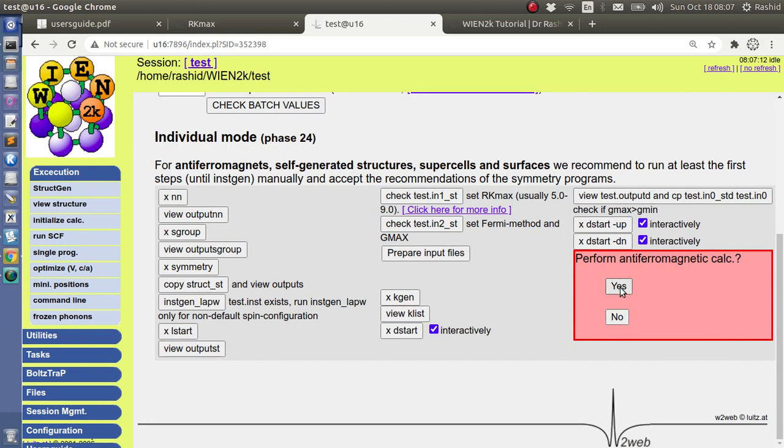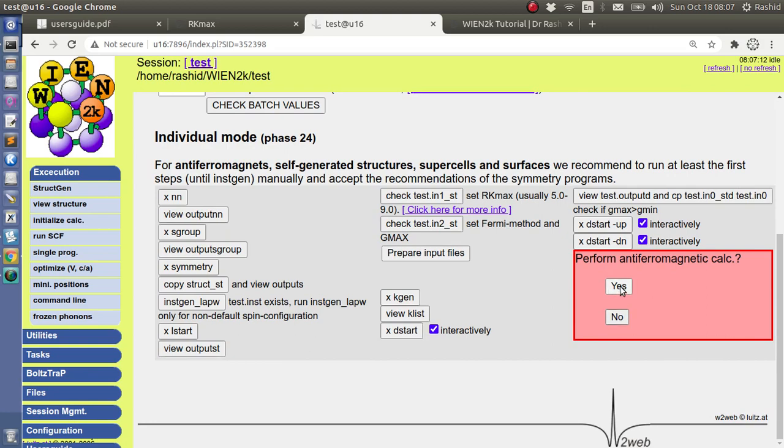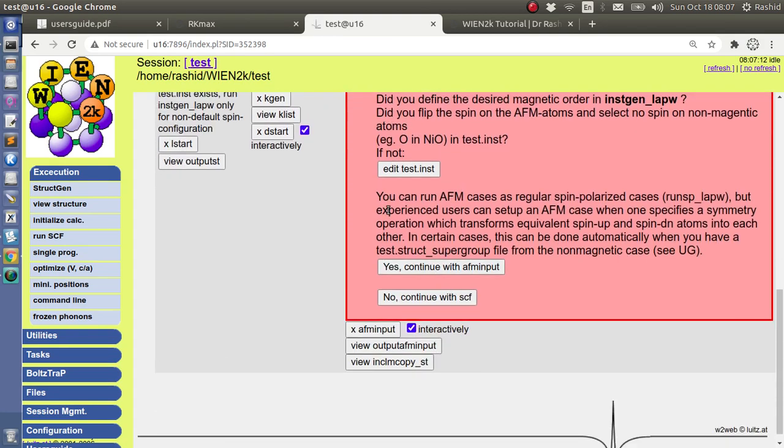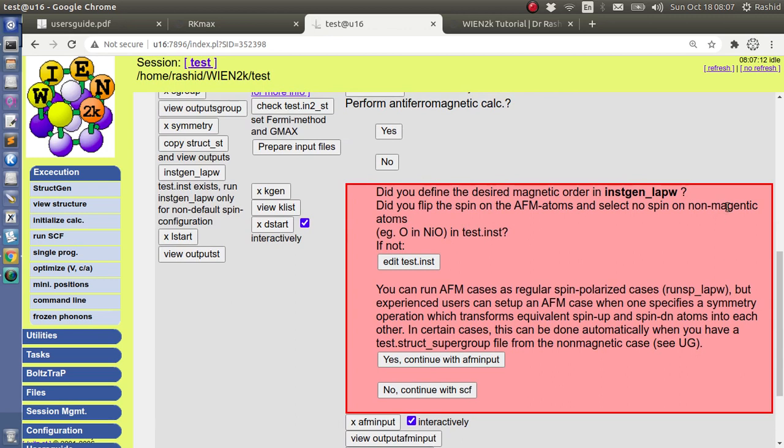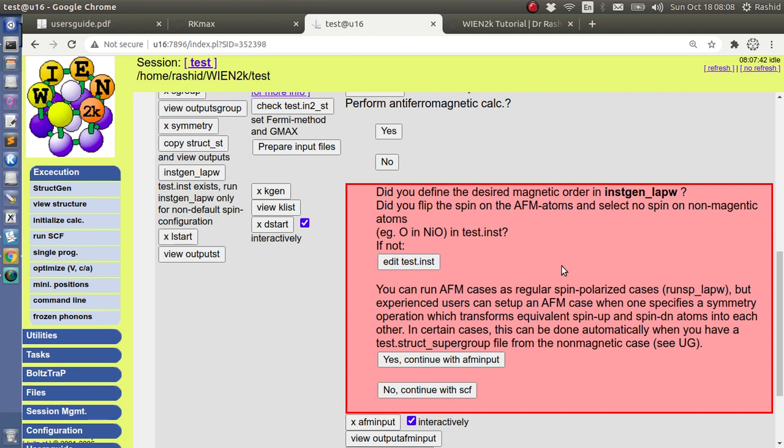Now if you like to choose the antiferromagnetic calculation, you can click here yes, but I will not do so. But I will show you what happens if you click yes. It will ask you whether you have selected them properly. And if you click yes continue, it will ask you to provide the rotating vector. Because when you do antiferromagnetic calculation, it is assumed that from one spin with a proper rotation vector you can go to the other spin. That is, it will do the calculation for one spin only, say for up spin only, and with that rotation vector that you provide it will calculate the down spin properties.